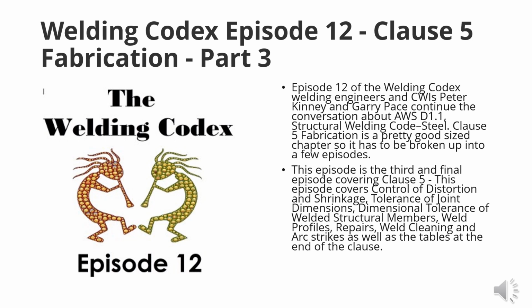But basically, peening puts a compressive stress into the surface of the weld. It could also be that as you're welding, you peen to relieve stress. Now in the code, it basically says you can't do it on the root pass or on the surface layer, or the base metal at the edges of the weld, except it does have some guidance in there for tubulars.